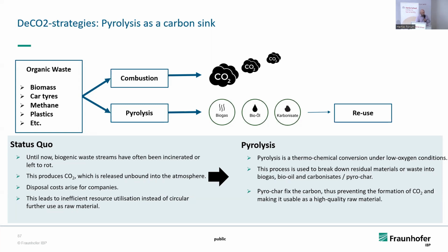If you use a pyrolysis technology, which works without oxygen, you get other products. You get a so-called biogas or synthesis gas, which contains hydrogen and carbon monoxide. Depending on the raw material, you get a highly valuable oil. And the mineralic waste is combined with the carbonizate. These products you can reuse again. For example, if you use biomass, after pyrolysis you can remove about 40% of the carbon as a carbonizate, and you avoid the generation of CO2. So this is clearly a climate positive technology.